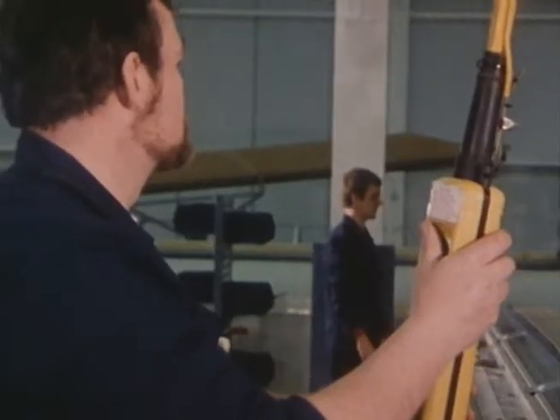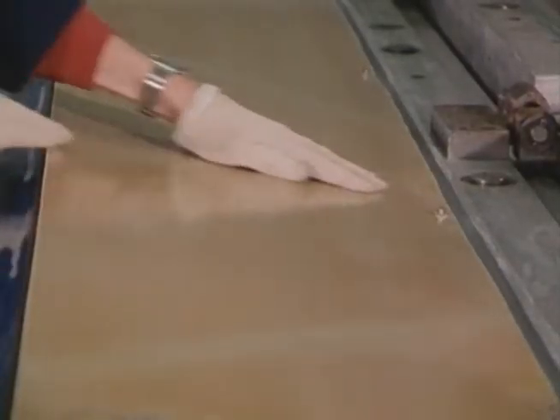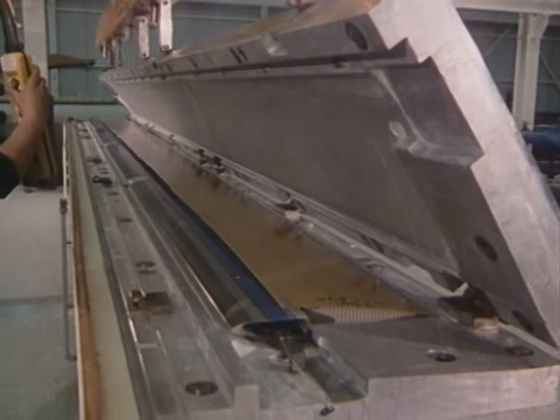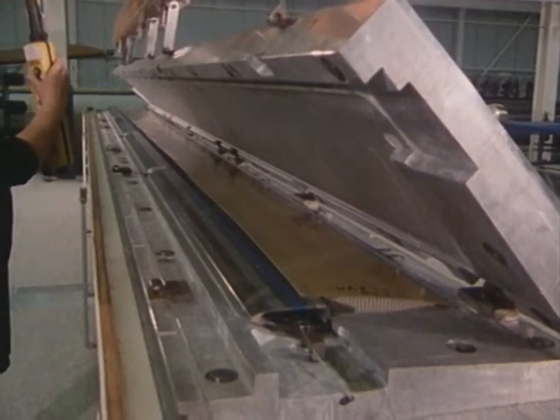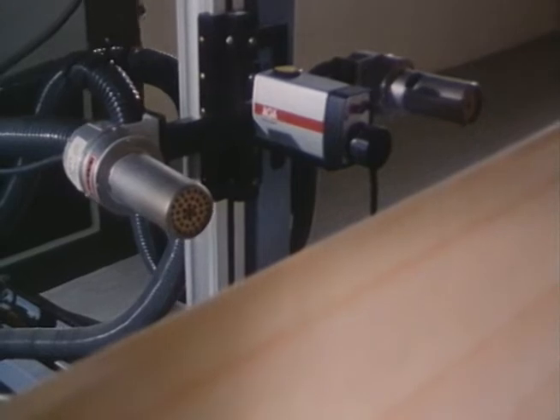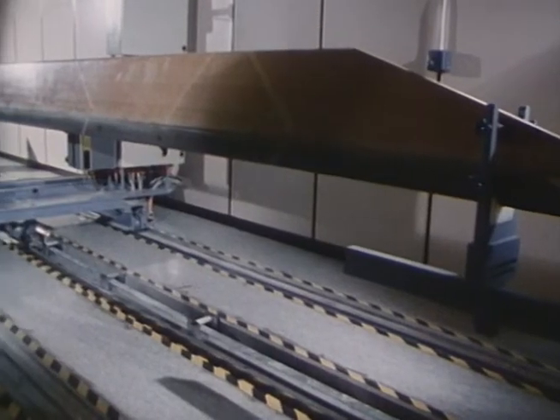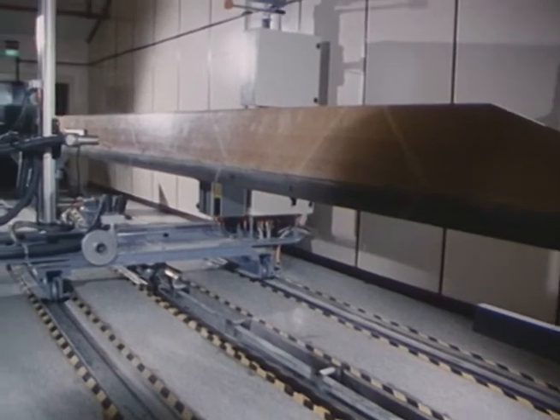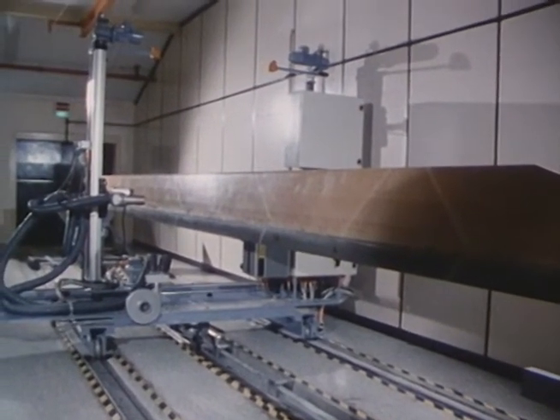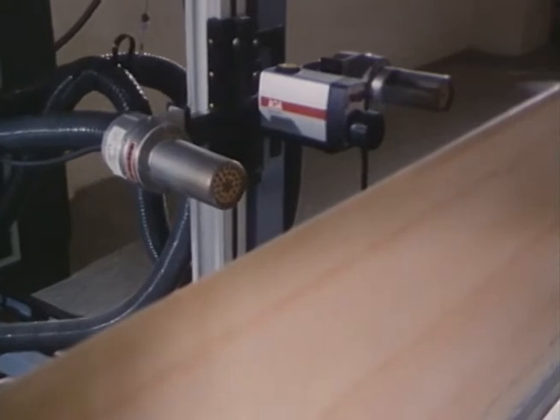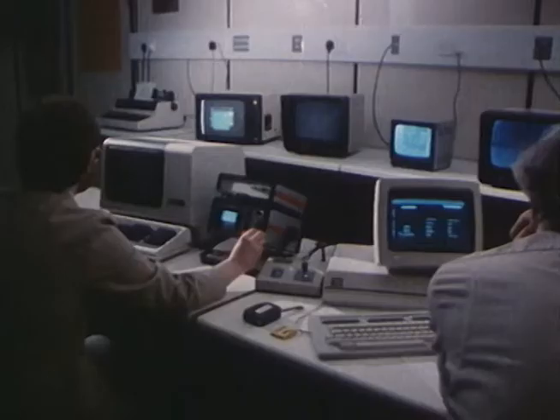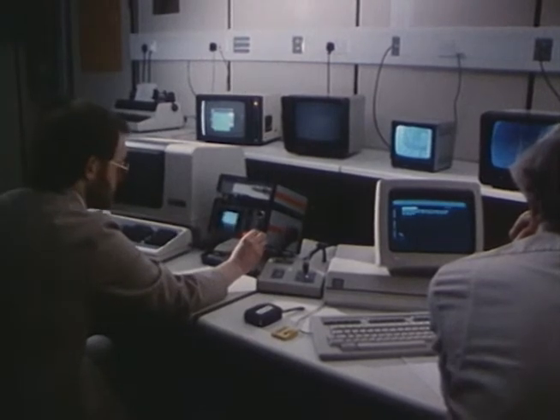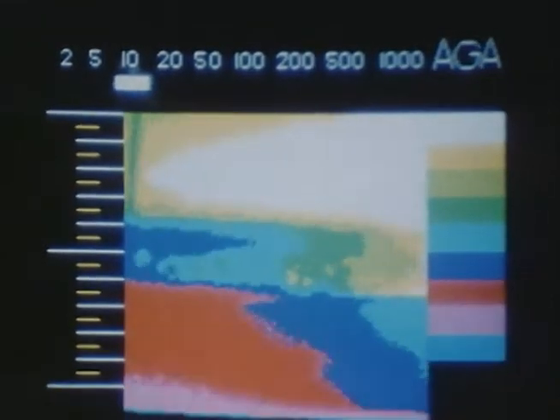When cured, the blade must be thoroughly inspected for bond integrity. Thermography is a method of non-destructive testing. Hot air blowers locally raise the blade temperature by 10 degrees C. An infrared camera observes the blade temperature. Since voids and debonds offer poor heat conduction, they can be detected by their different color temperature.